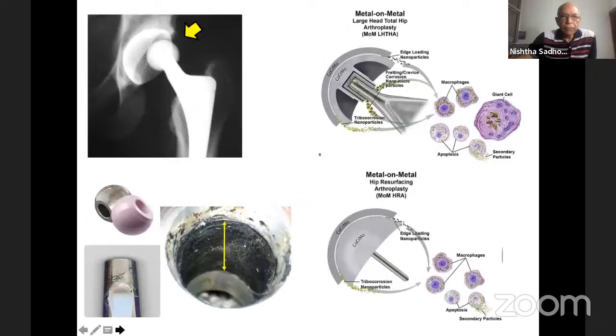So the radiological criteria, or what you can see in a metal and a poly, is a reduced distance between the head and the rim. That is, the head becomes eccentric. Now, this can apply to cemented, uncemented, any kind of coupling, which is cobalt on poly, or metal on metal, or even the coupling which is outside the joint. That is the so-called trunnion joint, on which you put the modular head, whether it is ceramic or the metal. So where this seats, you can have a wear, as it were, extra prosthesis wear, but wear all the same, and the net result would be the same.